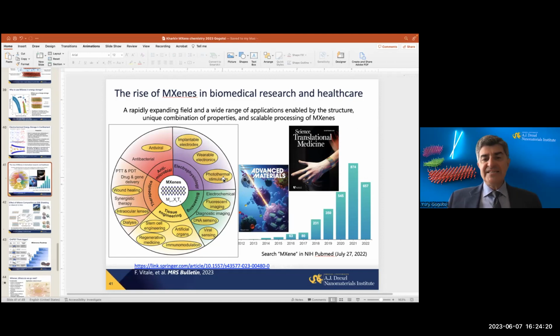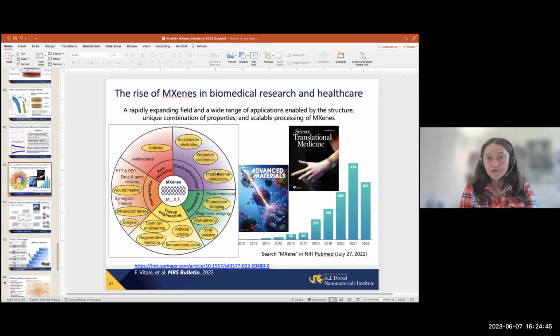MXene has a high negative zeta potential. So any drug molecules which are either positively charged, for example, having amino groups, or which have enough hydrogen bonding, hydroxyl or carboxyl groups, will be adsorbed on MXenes, and you can assemble them between layers of MXenes. And the related question: if it works perfectly as an antiviral or antibacterial material, is it toxic? Have you conducted some experiments regarding toxicity?